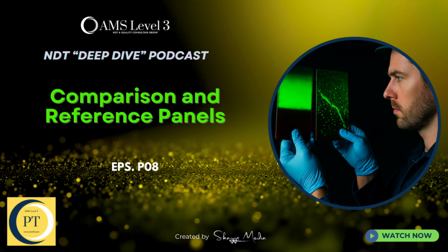But, okay, here's where the source throws in a really important point, almost a warning. Luminance gets you classified, but it isn't a direct measure of sensitivity. Can you break that down? Yeah, this is crucial. You might get the paperwork right, pass the QPL test because your system was bright enough under those lab conditions. But you could still miss flaws in production if your process control isn't tight. Luminance is just light output in a specific test. Sensitivity is the actual ability to find that tiny 2-micrometer crack out on the floor. Things like poor pre-cleaning can mess with luminance readings, but don't tell you if you can actually find the really small stuff.